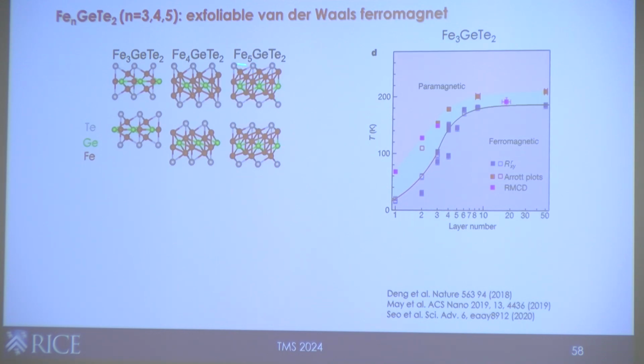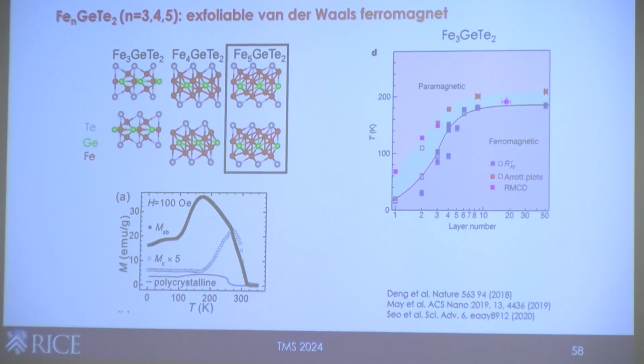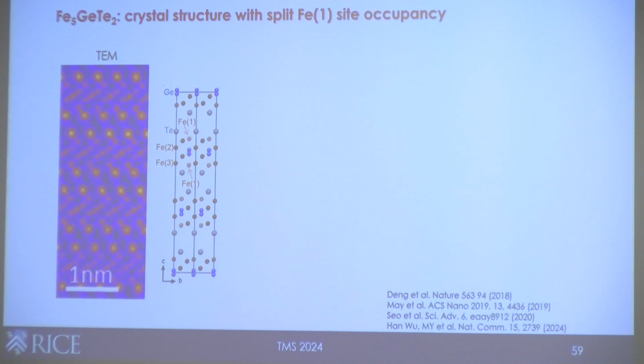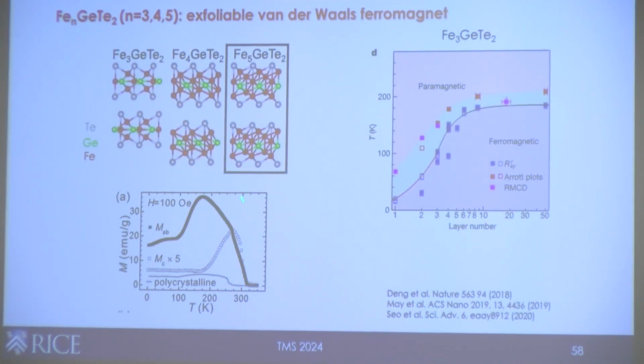and you have, depending on the different amount of iron, different Curie temperatures, and you can exfoliate them to a thin layer regime, and still retain the long-range magnetic order, which is interesting in its own right for two-dimensional magnetic order. But what I'm going to tell you about today is the third member, which is Fe5GeTe2. And it has a TC of around room temperature. This is the Curie temperature.